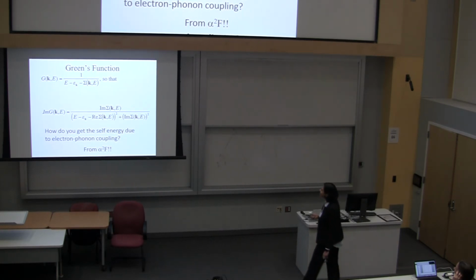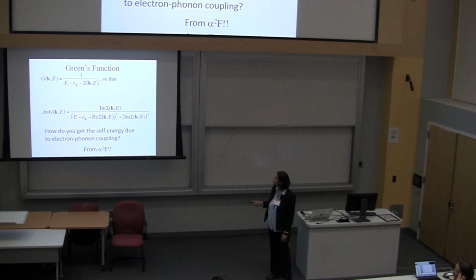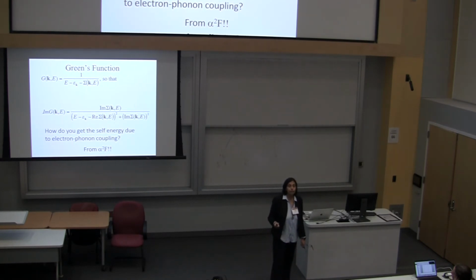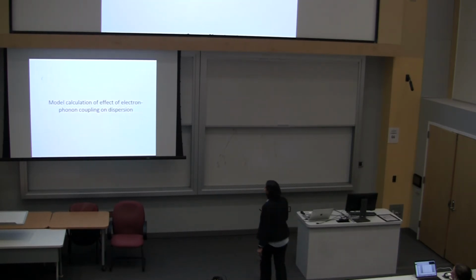So how do you get the self-energy due to electron-phonon coupling? You get it from alpha squared F. But measuring alpha squared F is not simple. So what we wanted to do was to measure alpha squared F by measuring the self-energy. That was our goal.